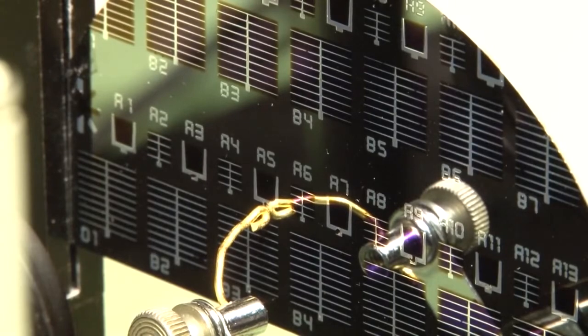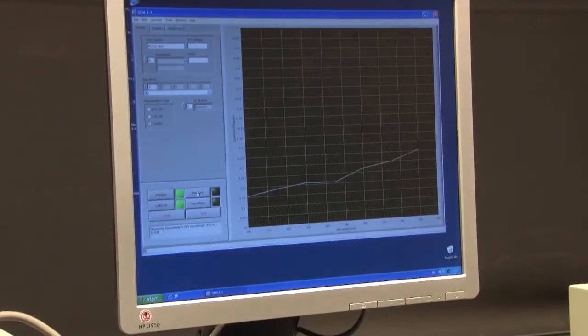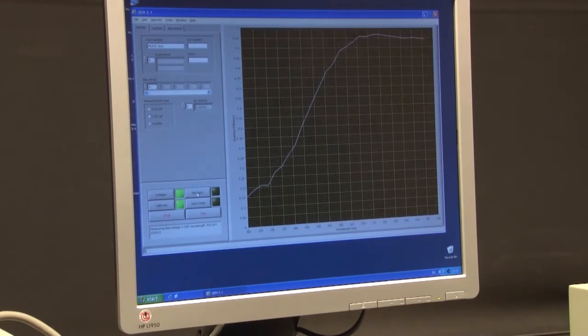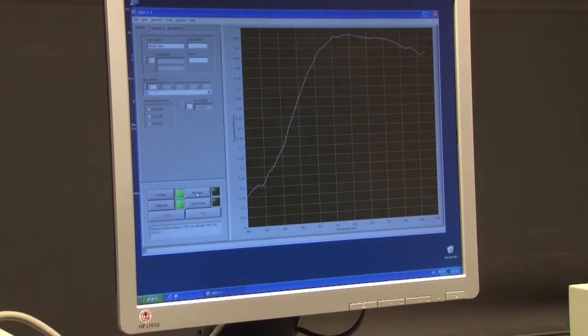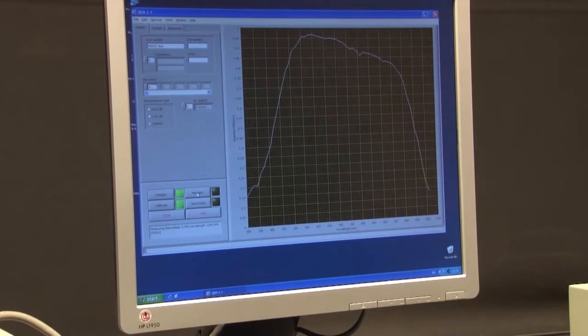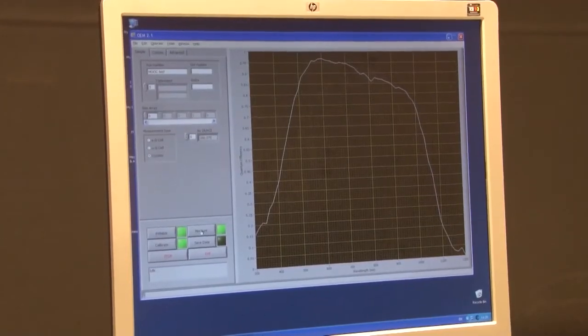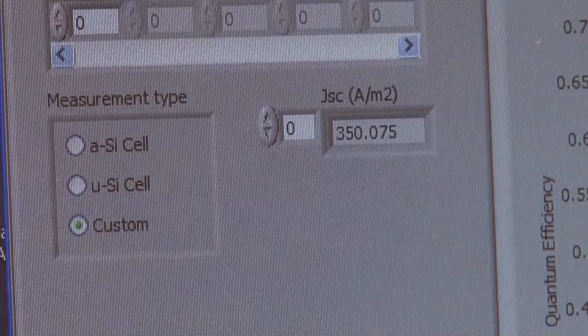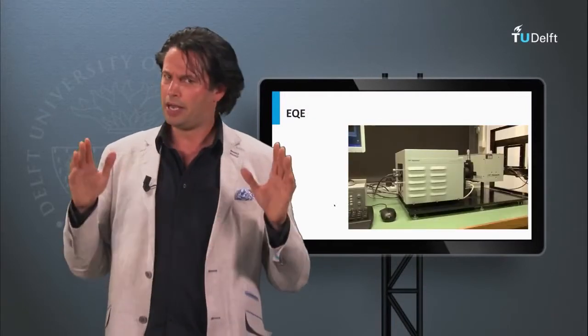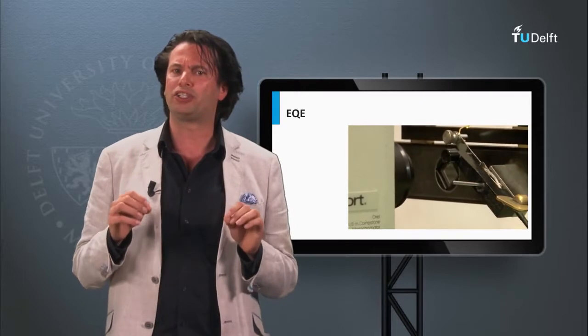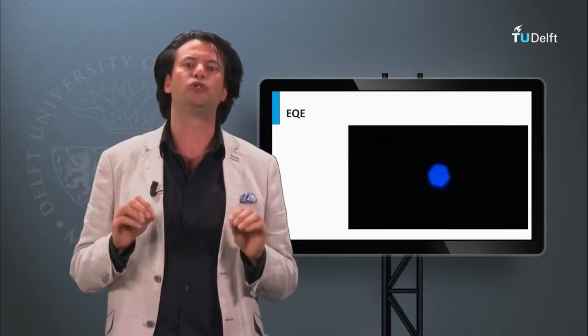In this example we measure the cell under short circuit condition, meaning no additional voltage bias is applied to the solar cell. The external quantum efficiency is measured as a function of wavelength, going from the blue to the red. The EQE can also be measured when additional reverse or forward bias is applied to the solar cell. The measured EQE in combination with the spectral power density of the AM 1.5 solar spectrum gives us the short circuit current density. In this case, the current density of the lab cell studied is 350 A per square meter, or 35 mA per square centimeter. If you want to report short circuit current densities of solar cells, you cannot rely on a single JV measurement — they have to be measured using an EQE setup.